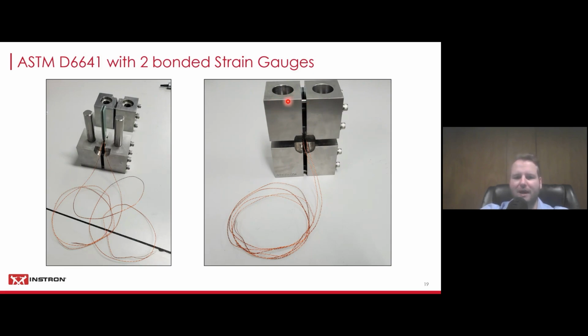It's very solid metal. And when you insert the top part, you need to have some amount of torque. Otherwise, it will just come falling down. So you need to find the sweet spot where you can safely insert the top part of the fixture. Like I said, it's relatively heavy, so it can be tricky. Before you load a specimen with attached strain gauges and wires, I would say, try the fixture out by itself without any specimens, and then maybe with some simple non-strain-gauged specimens to get a feel for it, to get some experience before you start loading expensive specimens that are strain gauged.